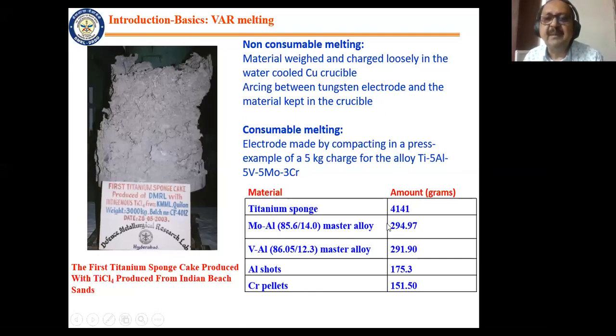Mostly in industry, you have what is known as consumable electrode melting, where you make an electrode. Here I'm giving an example of a 5 kg electrode, but the electrodes that are made industrially are much larger in tonnage, in several tons. I will show you the picture. So you make an electrode, attach it to the stub, and that acts as an electrode. The arcing is between the electrode and the bottom of the crucible, and it starts melting part by part and solidifies into the crucible, and that is called consumable melting. And here I'm giving you an example of an alloy Ti5Al, 5 vanadium, 5 moly, 3 chromium.